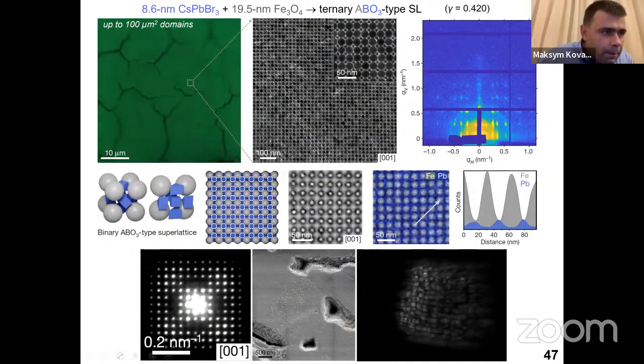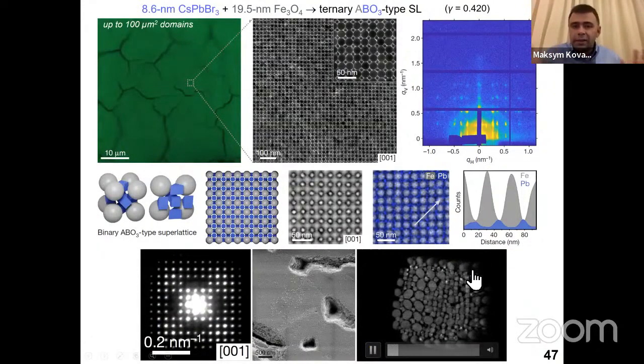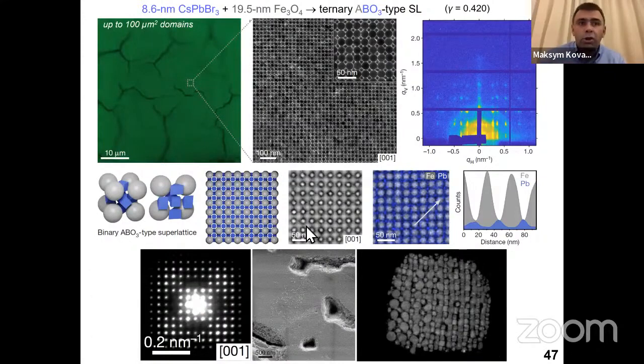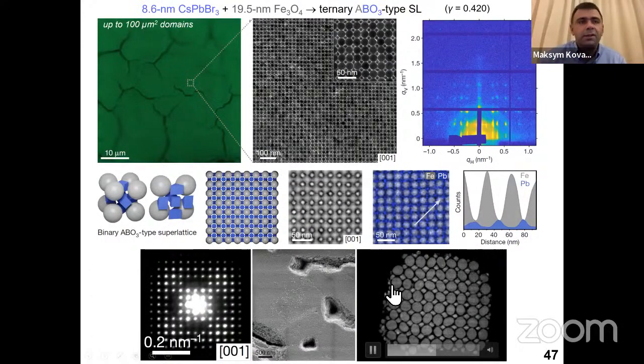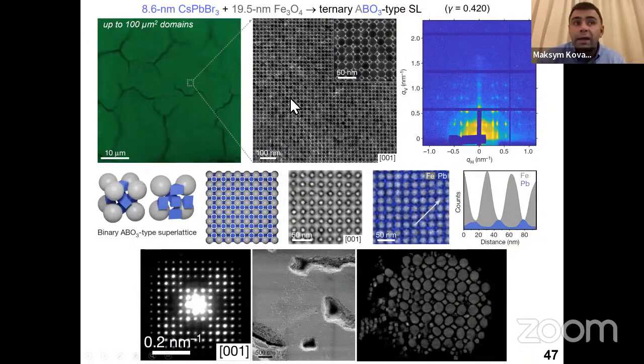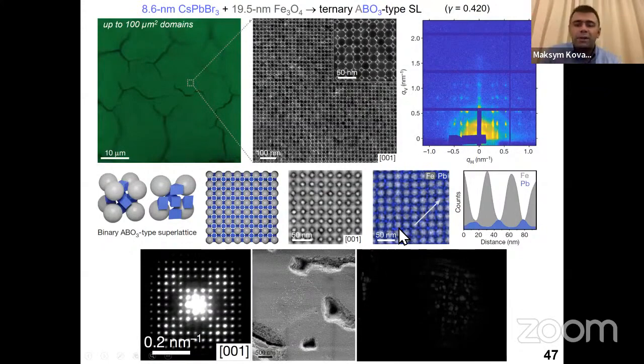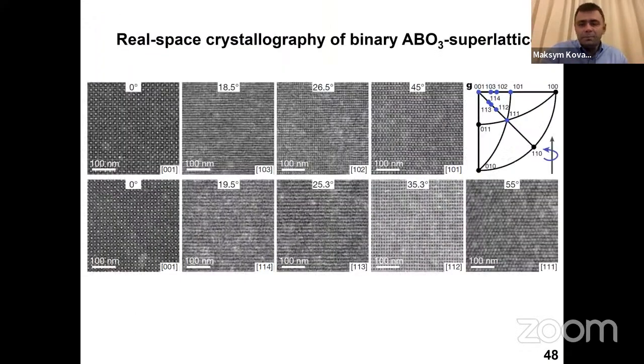And let me just show you that you can see it nicely in three-dimensional electron microscopy. You can observe it by all the techniques which prove this lattice, from X-ray diffraction to electron diffraction to direct observation in transmission microscopy. So it's a very peculiar example because you build a perovskite superlattice out of perovskite-based nanocrystals.